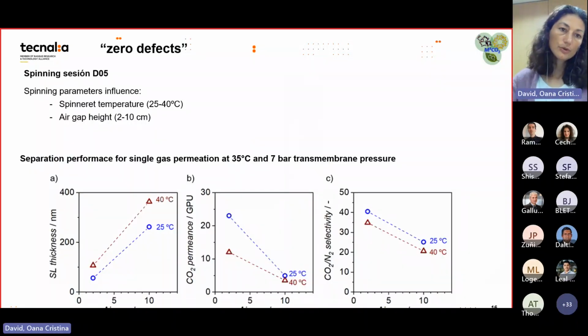And now if we go to the details of D05, speaking about the other process parameters, we also played a bit with the spinning temperature and with the air gap height. So here I show in this graph the extremes. It makes sense that if you increase the air gap height, you increase the selective layer thickness. So at a very low air gap, we got about 100 nanometers, and at a higher air gap, we had about 400 nanometers. At a higher spin temperature, the selective layer thickness was also higher.